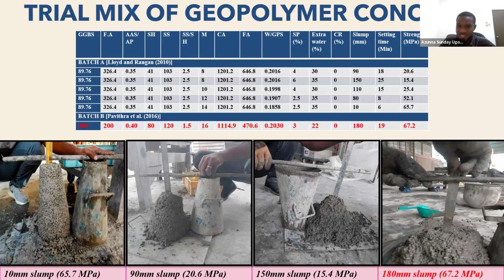Because in the lab, if you mix your solid part, your fine aggregate, your coarse aggregate, and then the moment you add the alkaline liquid, in less than 5 minutes, your concrete is solid. At times, you may not even be able to bring it out of the mixer. So most times, extra water is used. Now, if you check most journals, they recommend not to use more than 15% extra water. 15% of the binder is where you calculate your extra water from.